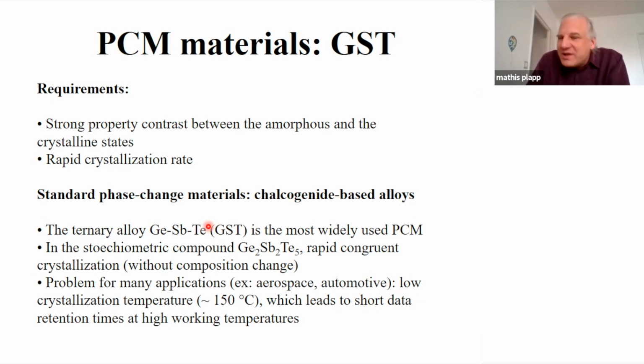Okay, but it has one decisive disadvantage. As you know, a glass is not an equilibrium state. So every glass actually would like to crystallize, and it's hindered from doing that because everything is just too slow. And so if you heat up the glass sufficiently close to the melting point, eventually it would crystallize. So you can define a crystallization temperature, which is not a thermodynamic concept, because it really depends on how long you want it to take.